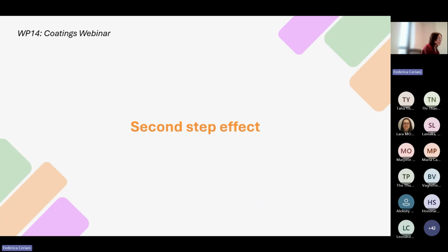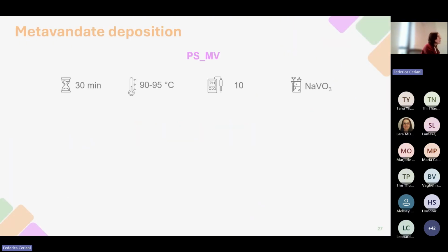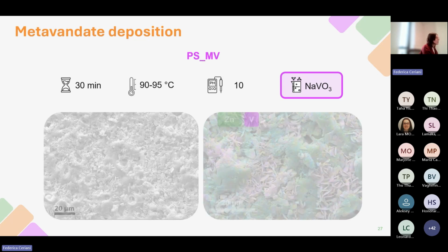The final variable that is considered is the performance of a second step during the post-treatment. So the PS_MV sample is immersed for 30 minutes in a solution containing sodium metavanadate heated to 90-95 Celsius degrees, and the PS metavanadate sample is produced. This sample is completely covered by large pita-like shaped precipitates containing both zinc and vanadium. Even in this case, the porosity of the original PEO coating is almost completely clogged, and a great sealing effect is obtained.